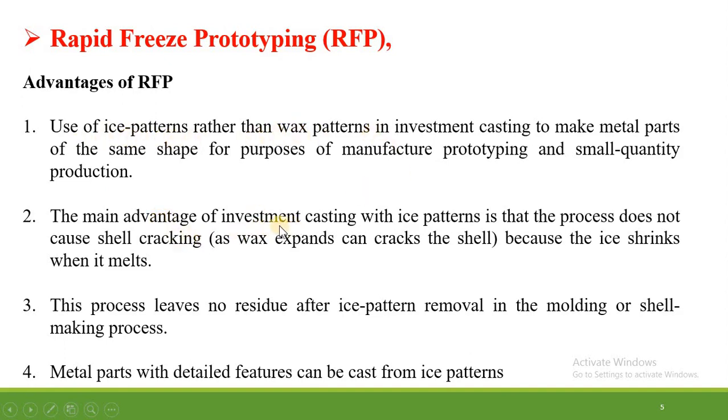The main advantage of investment casting with ice pattern is that the process does not cause shell cracking. Shell cracking is the biggest problem in investment casting, which occurs due to the expansion of wax, which cracks the shell. We know that when the wax gets solidified, it expands, which may create cracks in the shell. But when the ice melts, it shrinks, which may not crack the shell. So this is one more advantage of ice instead of wax.